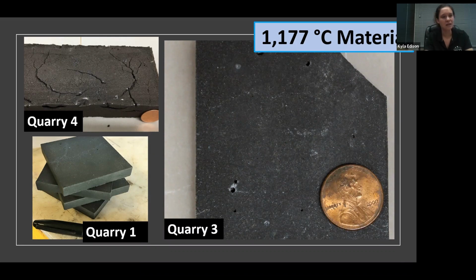That works at lower temperatures, but even just adding the 30 degrees, you're raising the temperature such that it's becoming hot enough that when it cools, if you let it cool naturally, you're basically subjecting it to thermal shock. And so in the oven itself, it just completely shatters.